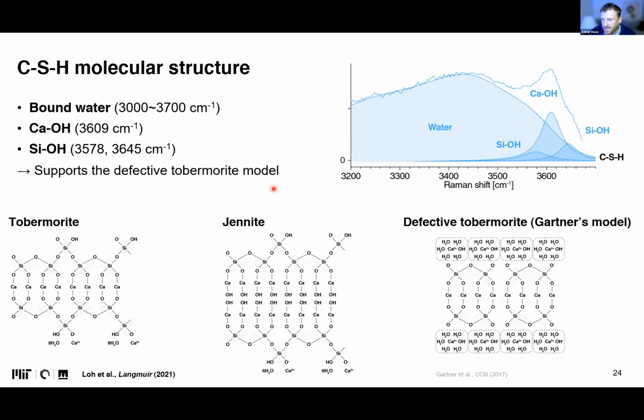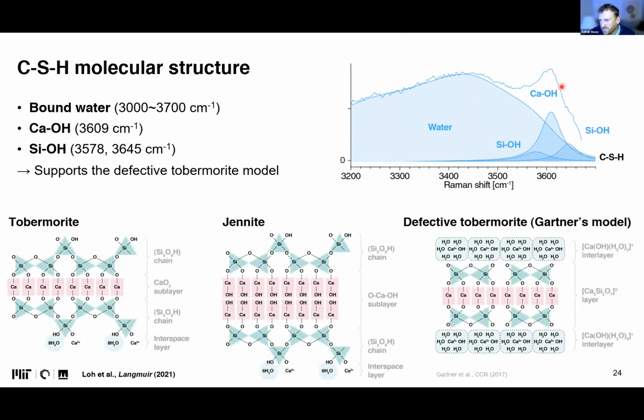If we look at this broad peak that remains underneath the calcium hydroxide, we notice that this is a peak of CSH, and of course it's broadened because it's disordered in general. Using this deconvolution here, we were able to confirm the Gartner's model for defective tobermorite CSH, at least in this specific case we studied. And here is the standard ordinary Portland cement sample.